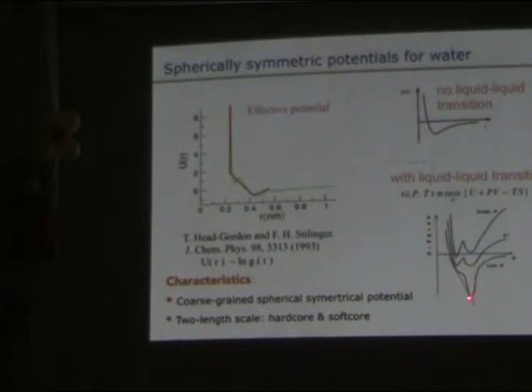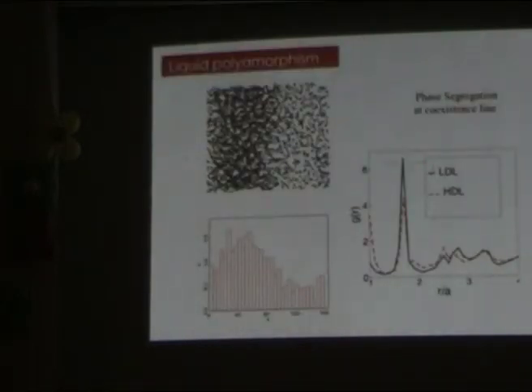For instance, at low pressures, the low density liquid is stabilized. But if you gradually increase pressure, you can see at some point, these two liquid phases can equally coexist. And at high pressures, of course, we can stabilize the high density liquid. So therefore, you can see that we have some indication. We are not starting from nothing. We have a rough estimate of what we can get. So we just run really simple computer simulations, molecular dynamics simulations. You can see that clearly. You can see they coexist as two liquid states. There's a high density and there's a low density.